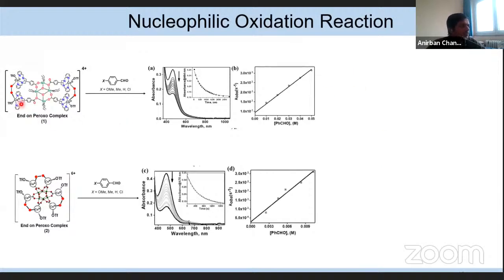So since it's a peroxo species, immediately I tried the nucleophilic oxidation reaction, because peroxo species are well known to show nucleophilic oxidation reaction. And this is the reaction with tetranuclear peroxo species with benzaldehyde, and you can see the decay of the characteristic absorption band, which follows a first order kinetics.